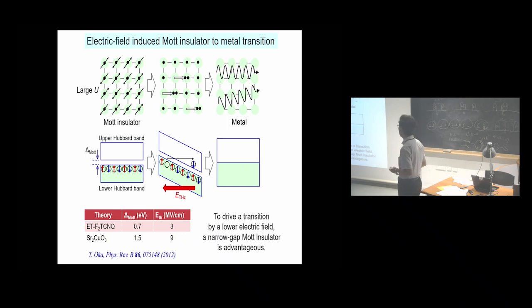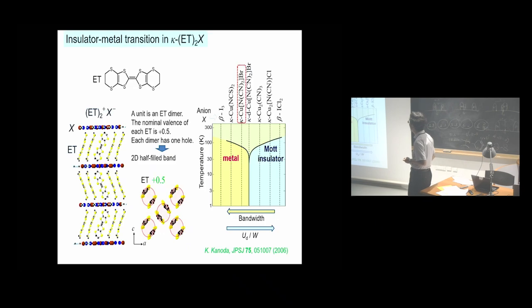The theory also predicted that the electric field necessary to generate carriers is very high. It is 3 megavolts per centimeter in the 1D Mott insulator ET-F2TCNQ mentioned before, and increases with increase of the Mott gap energy. So, to drive a transition by a lower electric field, a narrow gap Mott insulator is advantageous. Considering this point, we focus on this organic molecular compound called kappa-ET2X. In this compound, ET molecules and anion X molecules form layer structures like this.